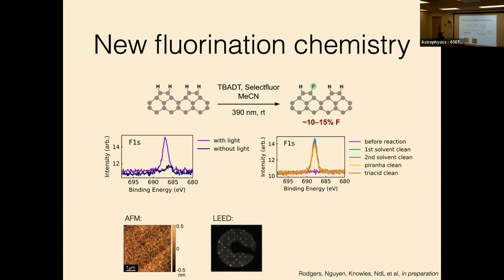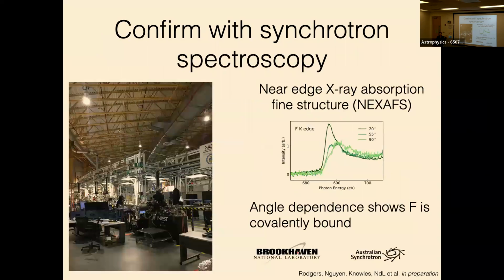The AFM looks clean, and we can even see this beautiful 2x1 reconstruction pattern in LEED that shows that it's a very nice and well-ordered surface. Okay, so that's all very suggestive, but now we can go to a synchrotron source to again do near edge X-ray absorption fine structure spectroscopy, and we take advantage of this thing that I mentioned earlier, where we can look at the polarization dependence of the signal, and we see that if we look at the fluorine edge, you see this clean polarization dependence, which really indicates that the fluorine is covalently bound.